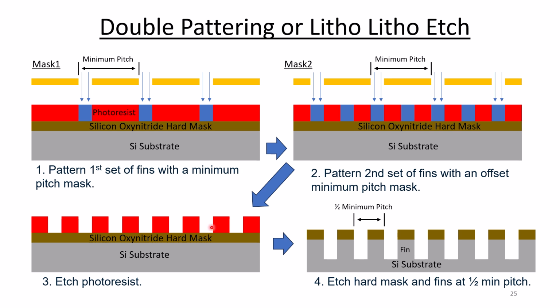Now, you might be able to do this with 3 masks or maybe 4 masks, but you can see that alignment between these mask layers is going to become very difficult after a while. You'd like everything to be perfectly aligned, but that never really happens. There's always going to be slight mismatches. So this works maybe for 1 or 2 iterations, but something better than this is needed. And by the way, this is why it's called litho-litho-etch, because you did a lithography step and then a second lithography step, and then you did your etch step.